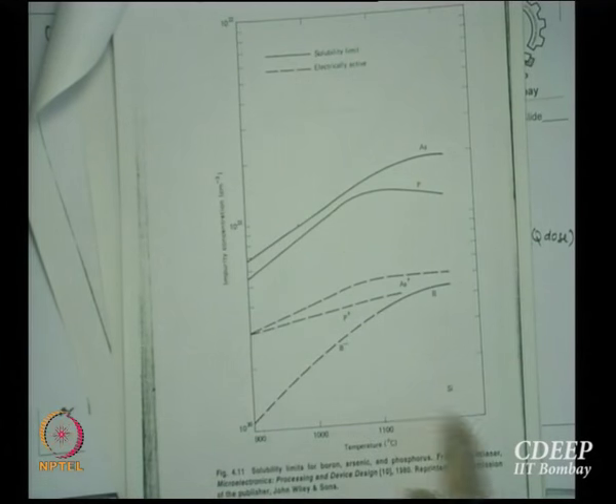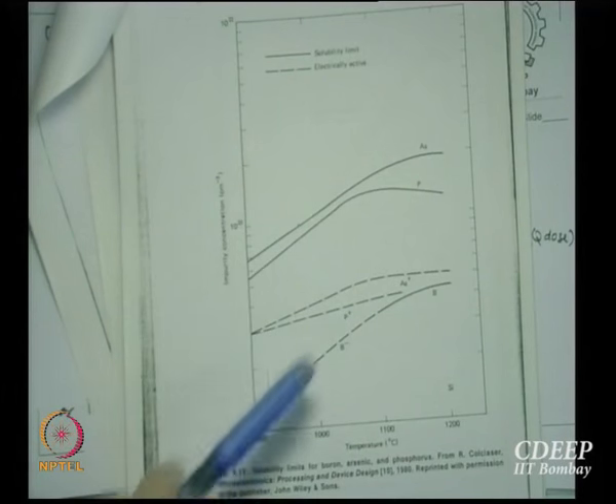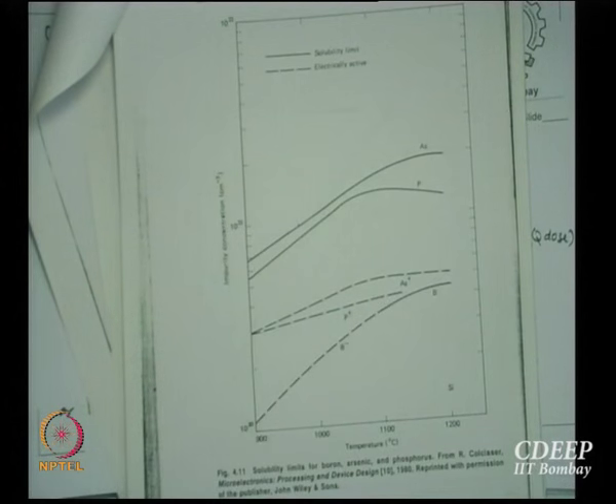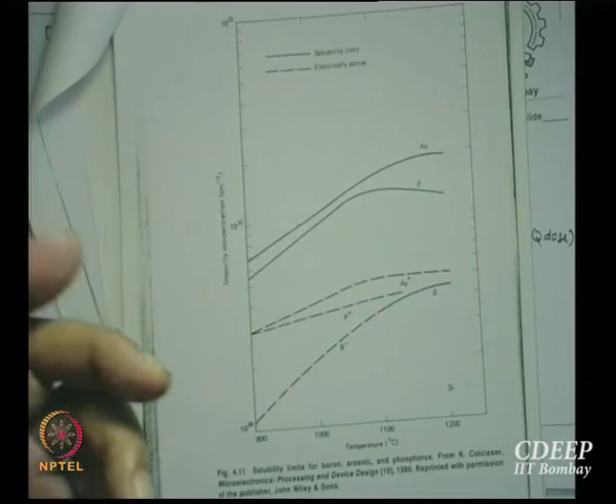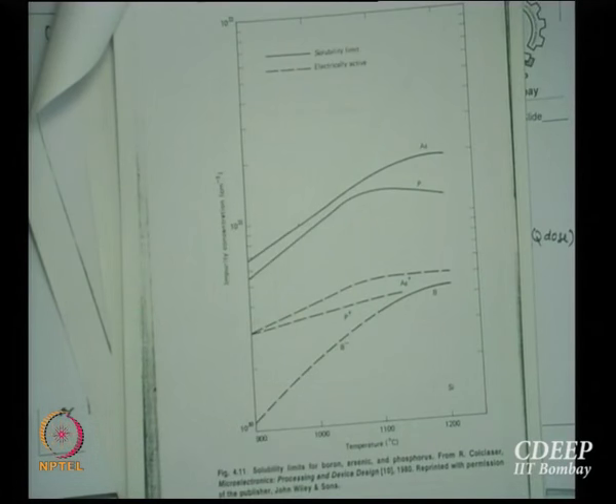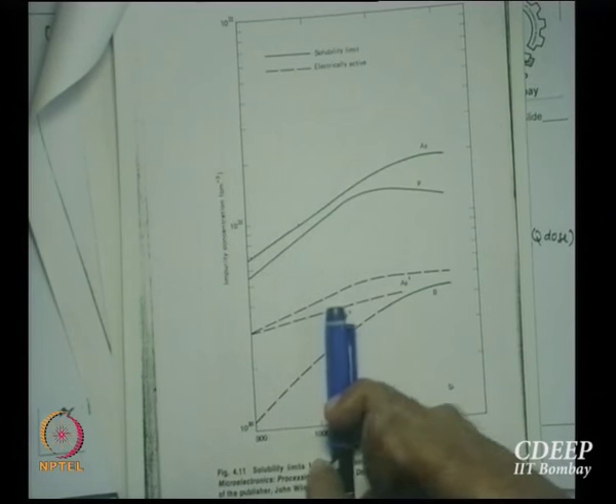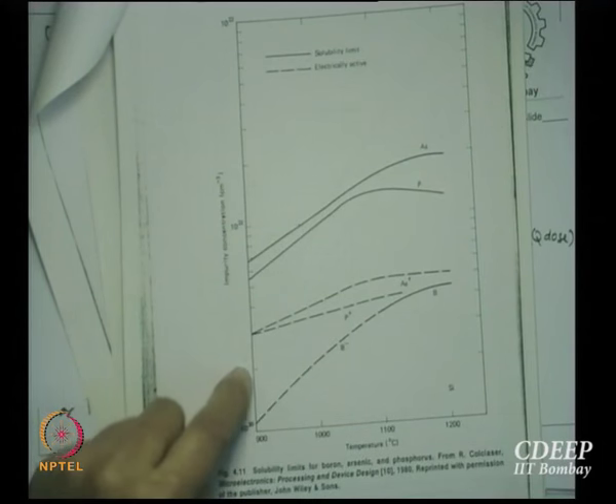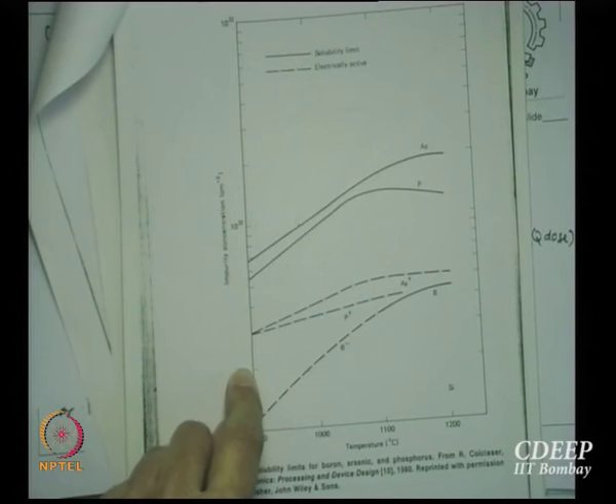So use solid solubility. This is temperature against solid solubility, and this is already written, solubility limits, and this is electrically active. So use the solubility limit N0; calculations should be performed from these graphs. So if you are doing pre-deposition at 1000 degrees for boron, go from 1000 to somewhere here, and this is 2 into 10 to the power 20, the concentration for N0 at 1000 degrees centigrade.